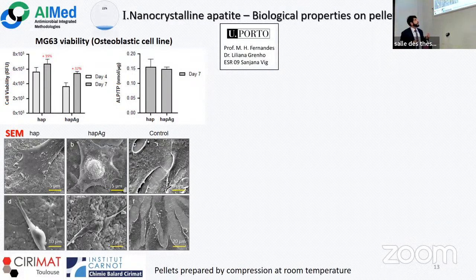As we can observe by this analysis, both on the SEM images and on the histograms, we have a good viability of the MG63 osteoblastic cells even on the pellets, and we can also observe that we have a relative increase that is higher between day 4 and day 7 for the silver apatite than for the normal apatite. And we can also observe the morphology of the cells, which is healthy, and that is the kind of result that we expected for healthy cells.